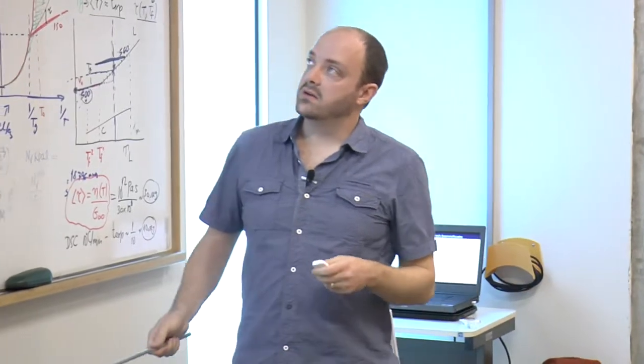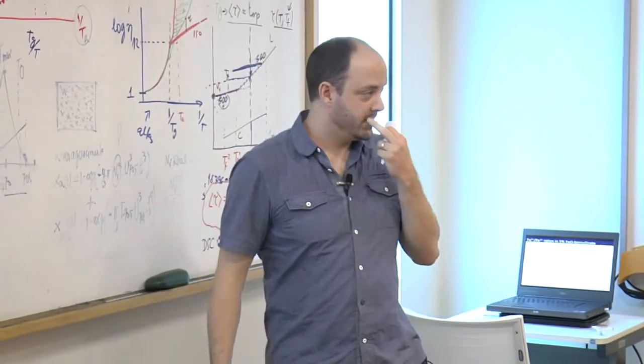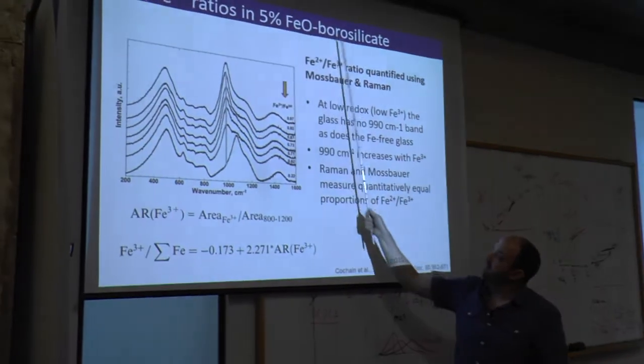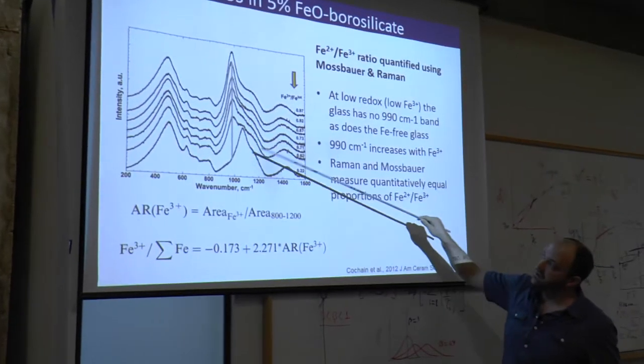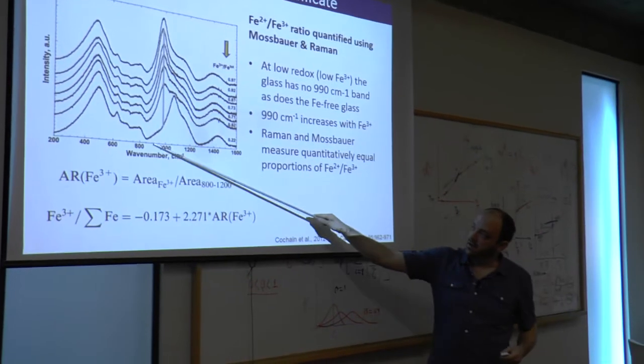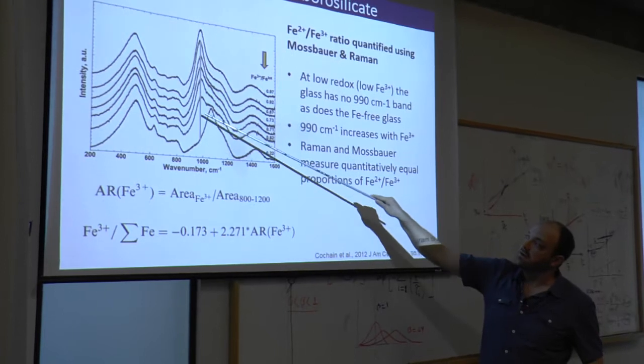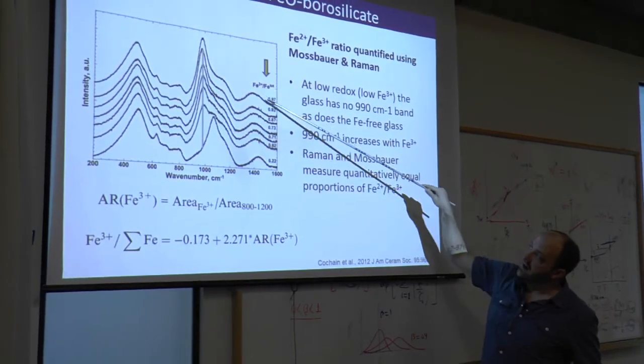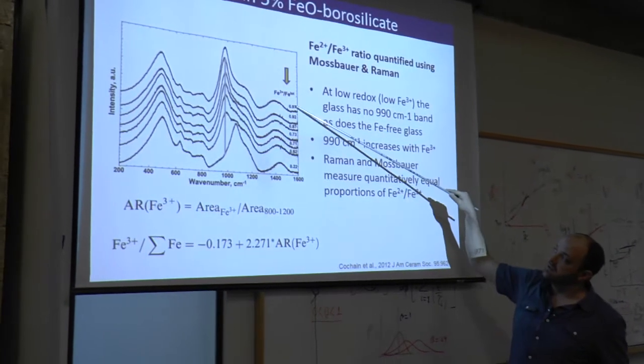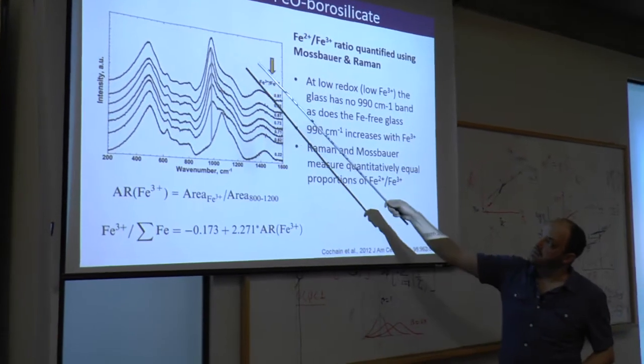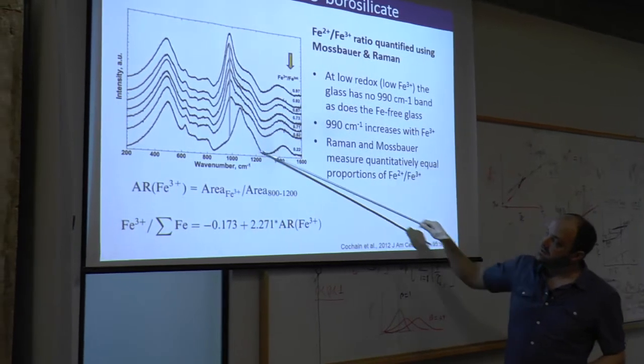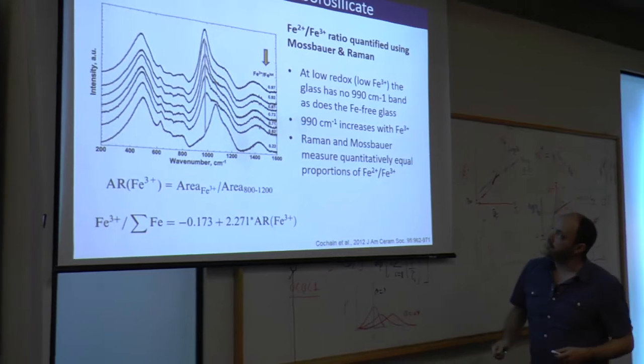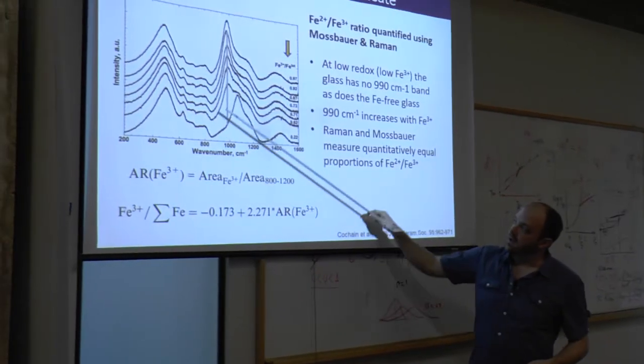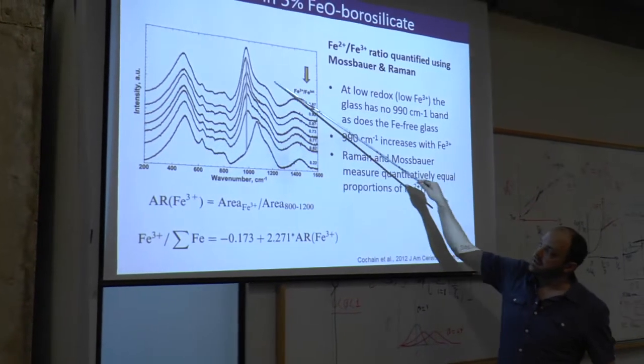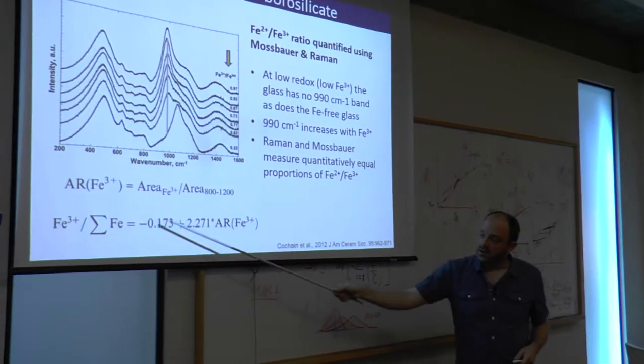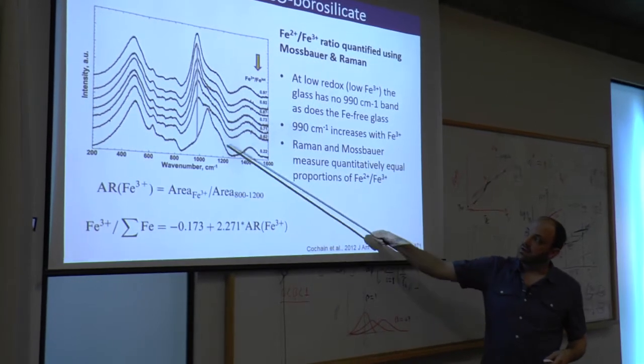Here's a nice study where they looked at borosilicate glasses which have had iron added to them. And this is another case where even just 5% iron creates another band that sits right on top of these Qn bands. So they had to model the spectra and do some sort of curve fitting to look at this band, which obviously increases as the Fe3+ increases. So they changed the redox in these glasses and have at the top here really high concentrations of Fe3+. Here, as you can see, there's almost no Fe3+ in the glass. And this is a case where they area normalized this part of the spectrum. They chopped this out and area normalized these bands to determine quantitatively how much Fe3+ relative to the total is in their glass.